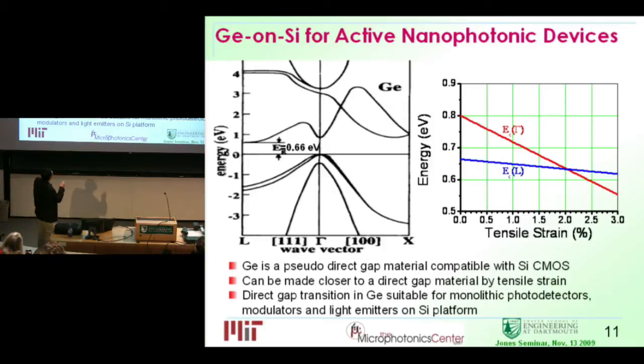On the other hand, there's a very nice property of germanium in that it's a pseudo-direct gap material. If you look up the germanium band gap in the textbook, they usually tell you this number, which is an indirect gap transition. In this chart, the vertical axis is energy, and the horizontal axis is crystal momentum. In order for a transition to happen, you not only need to match the energy difference, but also need to match the momentum.